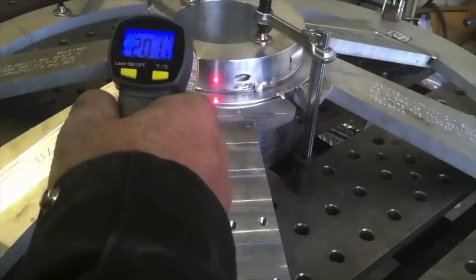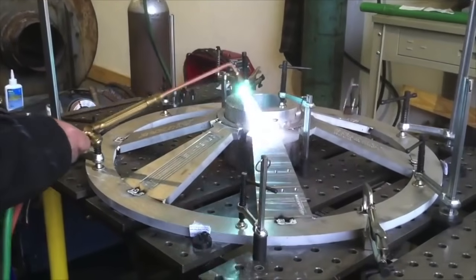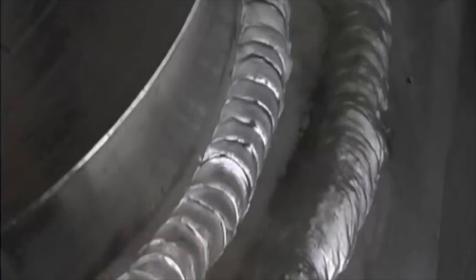Let's take a look at aluminum. Some aluminum alloys can be strengthened by heat treat, and some can only be strengthened by cold work. And we preheat aluminum, again, for a very different reason, mainly to just kind of assist in welding. It takes less amperage to weld it once it's preheated. It also helps a lot with porosity. Some aluminum alloys, mainly 6061 is a really common example, can be strengthened by heat treatment. But that doesn't mean it's strengthened by heating it up and quenching it. It's strengthened by holding it in an oven at an elevated temperature for several hours.